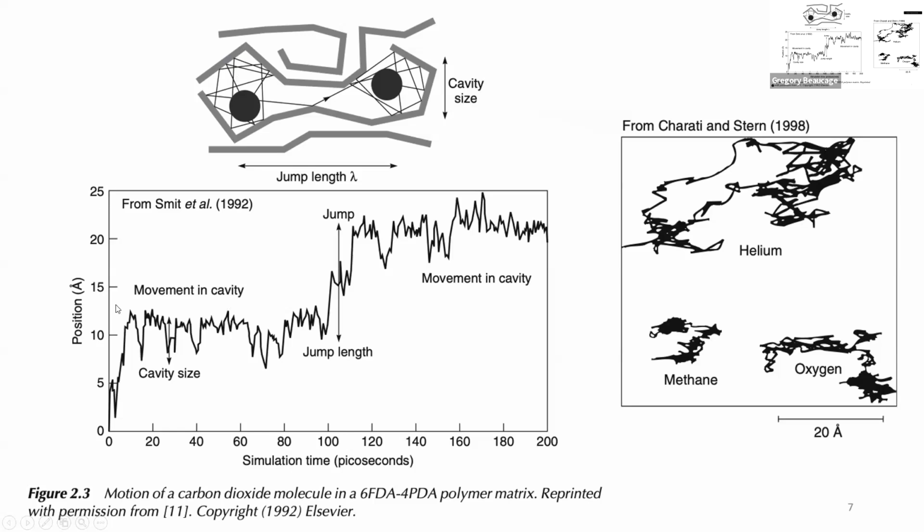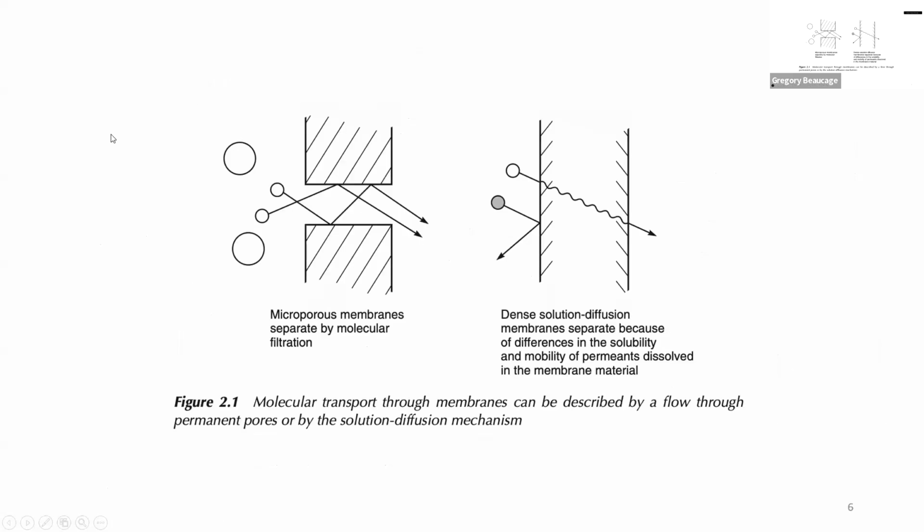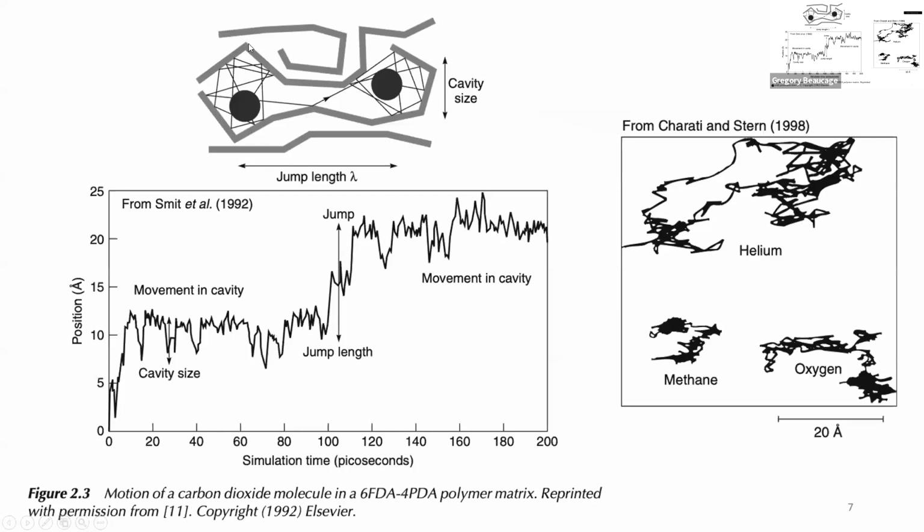It turns out when you do simulations of this, just like polymers and some gas molecule going through a polymer, like polyethylene wrapping your food to keep the moisture out of your cornflakes, it's a typical example, right? This is the kind of thing that actually happens. Get stuck in a little well region where the water can be happy, and then it suddenly randomly pops through a hole. So you get a jump. The motion is actually jump, stuck, kind of thing.